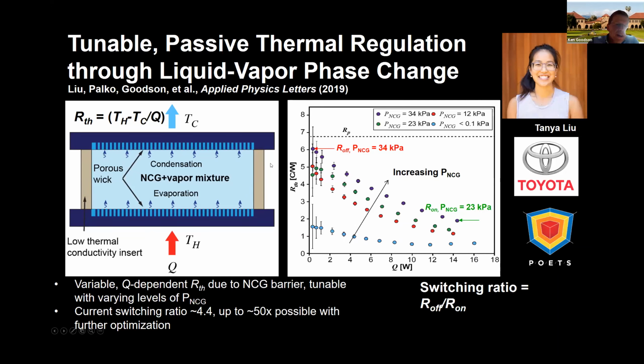And the application of this device is, for example, in the startup phase of an engine, in a diesel engine, where you want it to be well insulated early on. On a cold day, you'd like it to retain heat, but once it gets to a certain level of heating and temperature, you would like it to become more effective and cool itself more effectively. And so what happens here is, as you approach the phase change temperature, you start to have much more effective heat transfer, and the insulation properties break down. And you can tune this by means of the non-condensing gases.